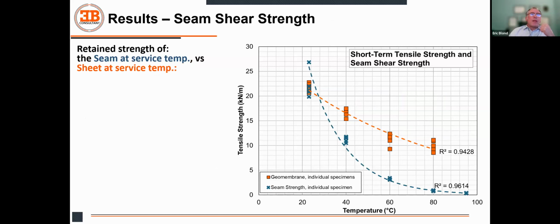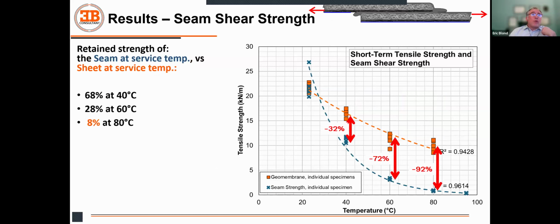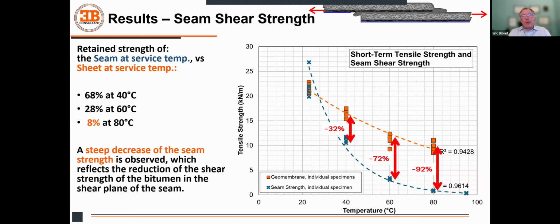Now, if we look at the seams, again, now I'm comparing the retained seam shear strength of the BGM with the sheet strength at the temperature of interest. So in orange here, you can see the sheet, and in blue, it's a seam. You can see a reduction of 32% at 40 Celsius, an additional 72% at 60, and an additional 92% at 80 Celsius. So really, we can see a very steep change of seam strength property.